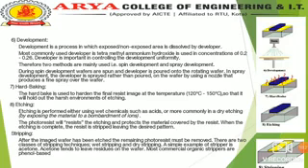The hard bake is used to harden the final resist mask at the temperature 120 degree centigrade to 150 degree centigrade, so that it will hold out the harsh environments of etching.